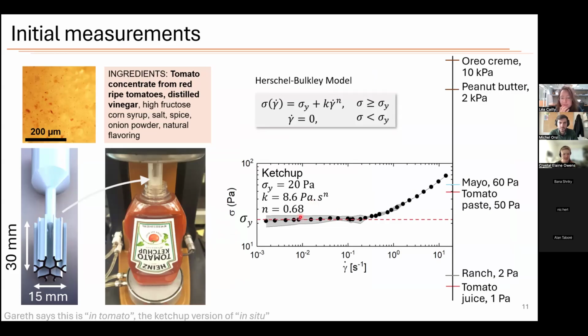And you can see it has the characteristic regions. It has this plateau with yield stress, and then it has this flowing region once you get to higher shear rates. And this data was measured for the average of 5 runs. So you can see there's a little bit of error here around the yield stress. But this is the model fit.